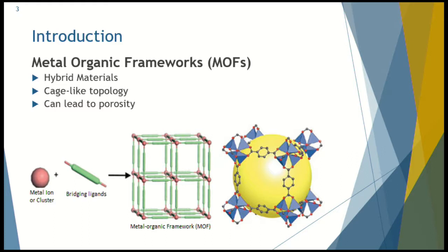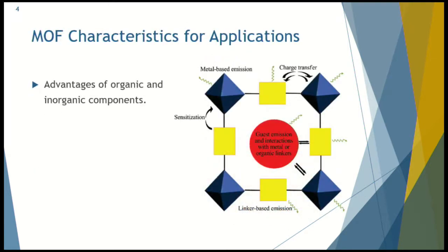Now, these materials have inherent characteristics that make them attractive materials for functional materials. For example, you have both the advantages of the organic as well as the inorganic components. And in this specific example for optoelectronic applications, you can have linker-based emission as well as metal-based emission. Furthermore, you can have interactions between the organic and inorganic components, such as charge transfer mechanisms or ligand-sensitized emission, which can enhance, or sometimes even new properties can arise due to these interactions between them.